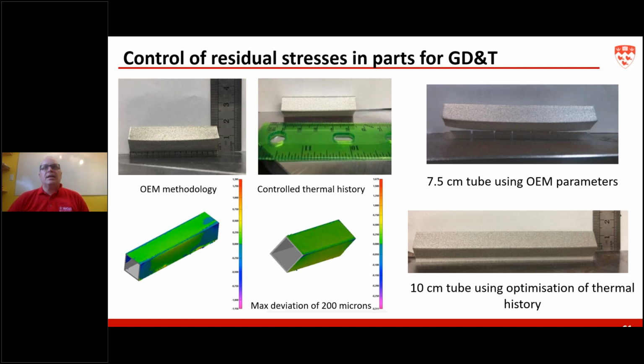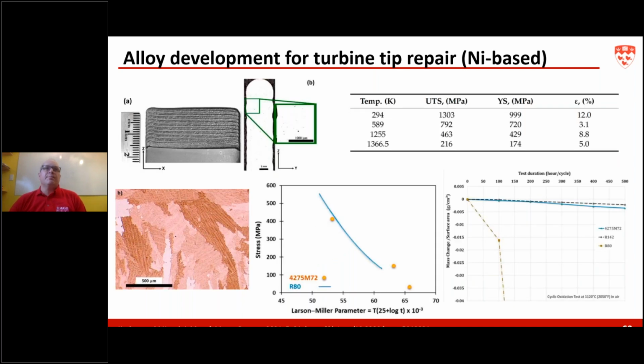The next slide, to finish on the examples, is alloy development. Turbine tip repair is quite an important field. And with some sponsors, we've worked at developing new alloys that could have what we call, again in the field, high gamma prime, so really high strength at high temperature. We've developed a few alloy compositions that can now be used just to refurbish the tip of the blades once they are worn. So what you have here on those slides are a couple of results that we've obtained: extremely high mechanical properties at high temperature.